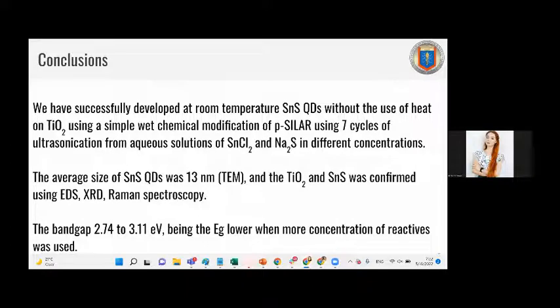And the samples that we obtained had 13 nanometers. That was confirmed by using EDS, X-ray, and Raman spectroscopy. And the band gap that we found for the material was between 2.74 and 3.11 electron volts, being lower band gap when more concentration of reagents was used.